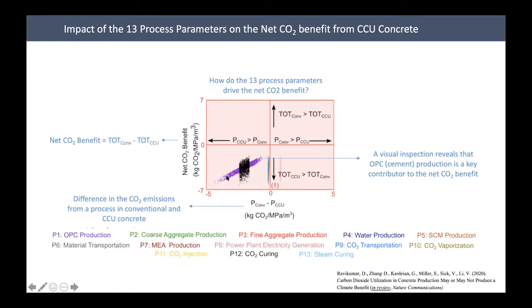As you can see over here, in this scatter plot, the purple dots seem to be very dominant. The purple dots correspond to the consumption of OPC. OPC is nothing but cement, ordinary Portland cement. So that seems to be driving the net CO2 benefit. In this case, the background of the graph is red. So it means that in this specific data set, CCU concrete is more burdensome in terms of climate impact when compared to conventional concrete, and OPC is the key driver. The difference between the amount of cement consumed in CCU concrete and in conventional concrete is driving the net CO2 benefit, which shows that CCU concrete is more burdensome than conventional concrete.